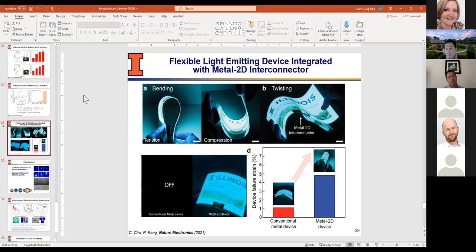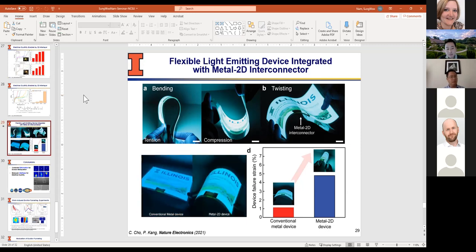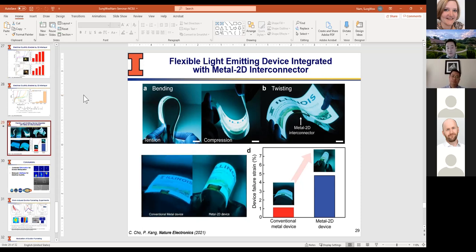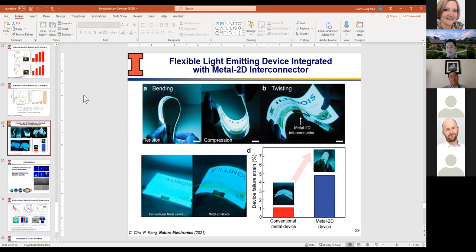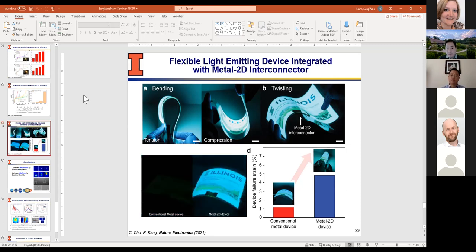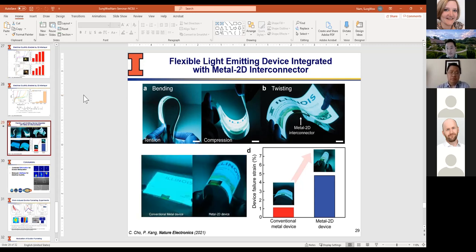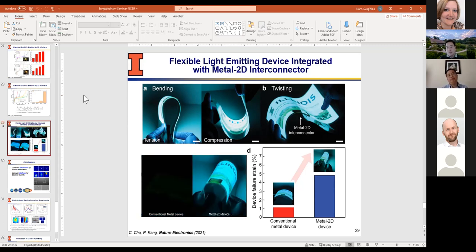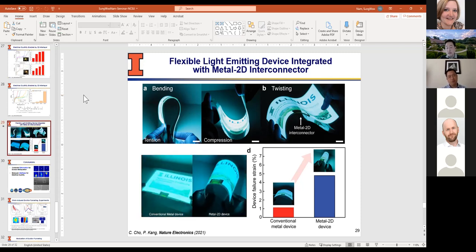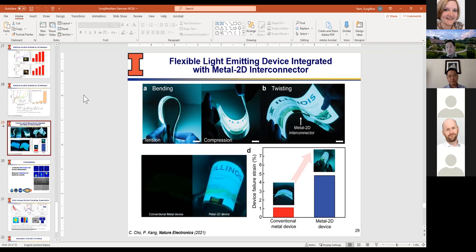So with flexible devices, if the strain is applied, you'll see a change to the optical band gap. That's well established. You see about 50 millielectron volts change per percent strain, roughly. That depends on whether it's uniaxial or biaxial, but a rough number would be about 50 millielectron volts. With respect to drift, you need a gradient in real space or through some direction. In that case, pure bending won't do anything for that. It will only change the energy.